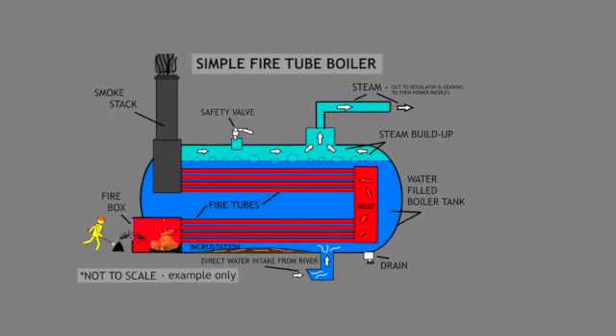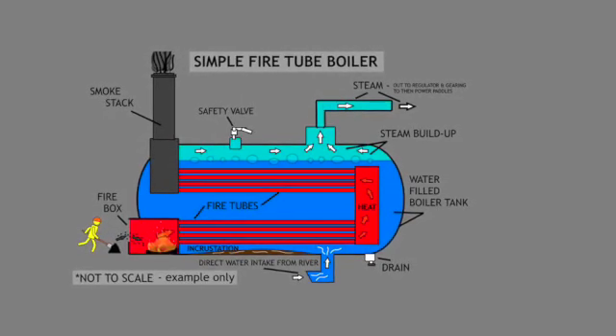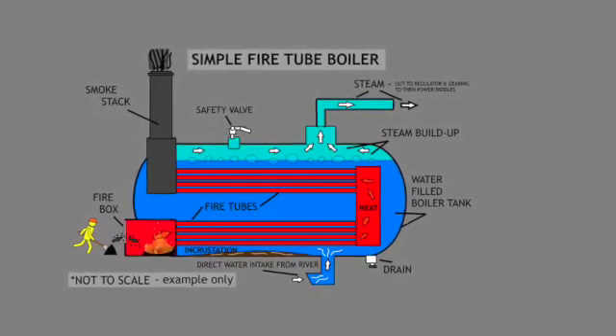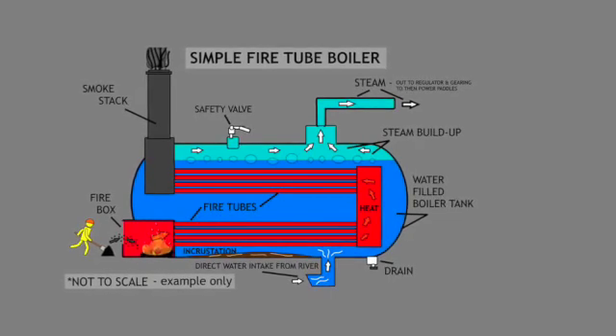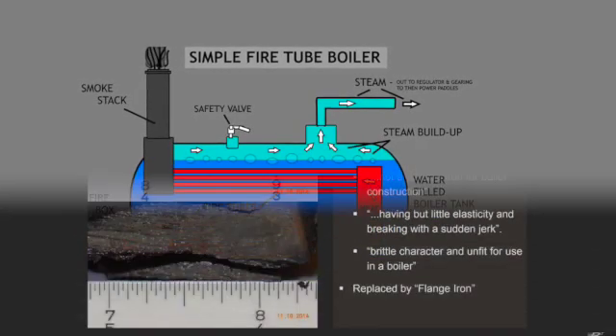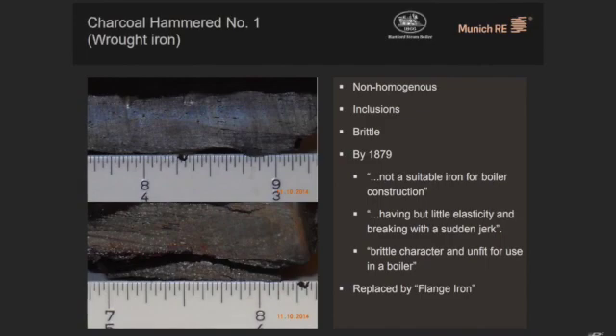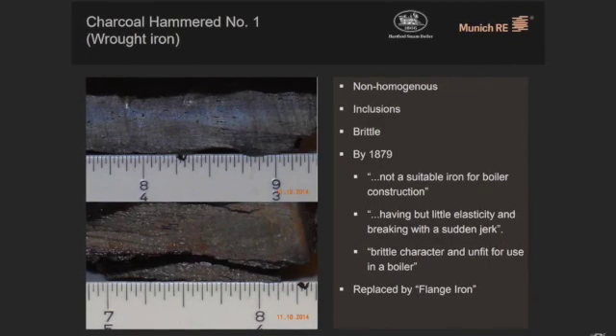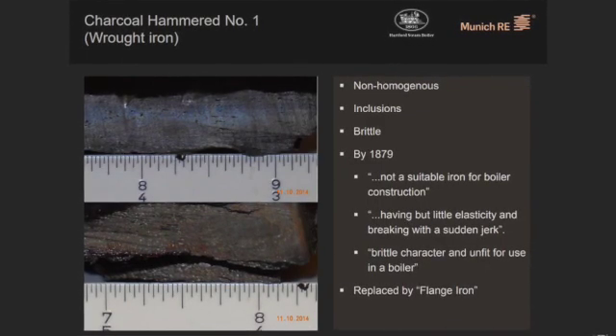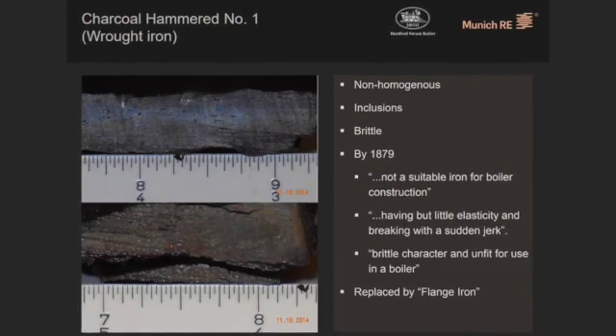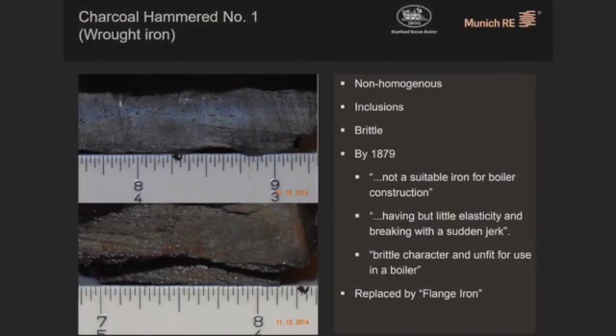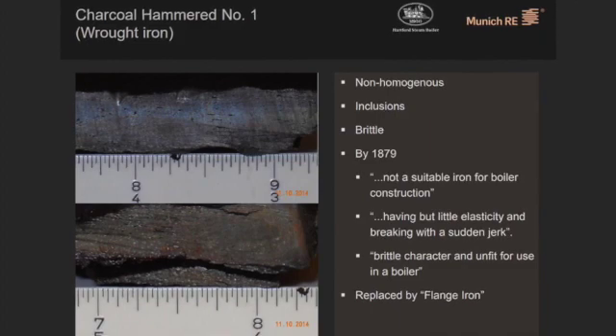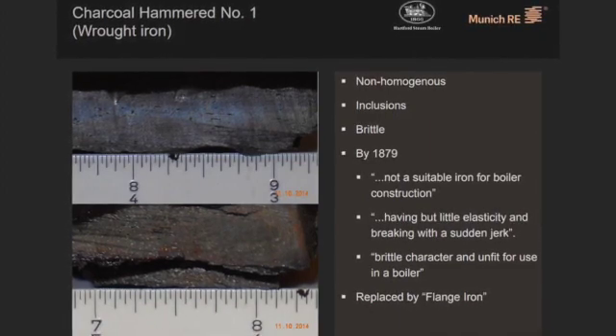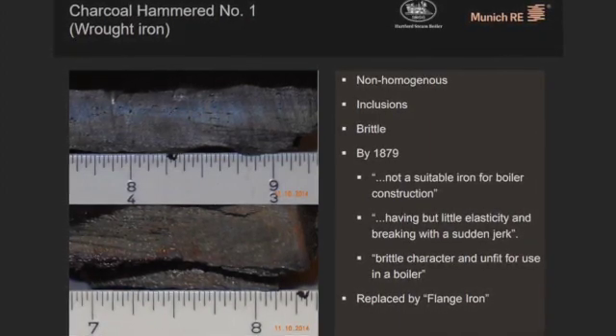The third factor is the diameter and proximity of the boilers to one another. Each boiler was constructed with 24 5-inch flues so closely packed to each other that cleaning was incredibly difficult and inefficient, especially due to the sediment buildup. The inability to clean the flues led back to factor 2, creating hot spots, which ultimately failed the material.